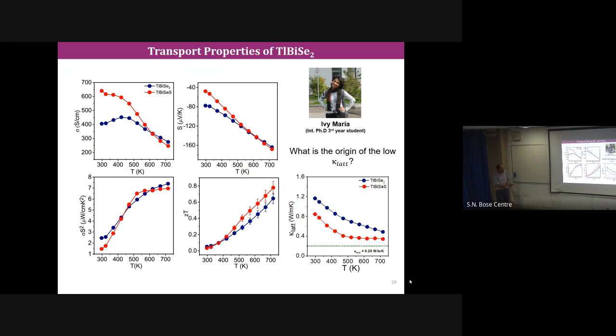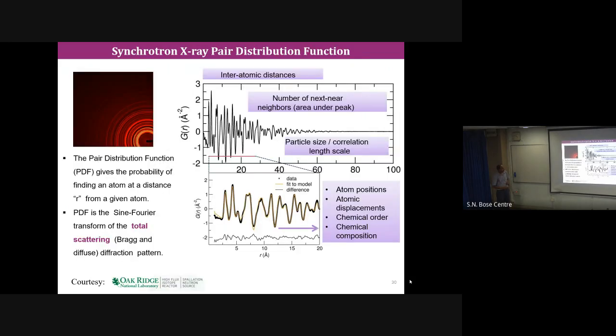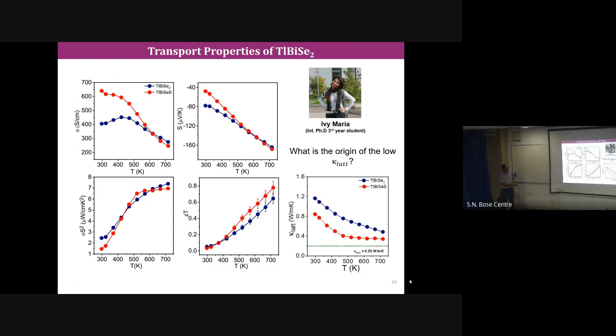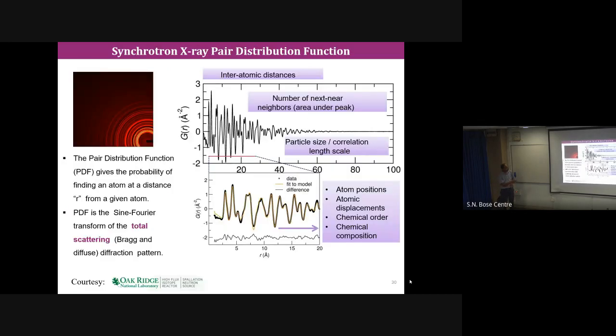So then we try to understand what is happening here. Why does the compound show very low thermal conductivity? Because you see, without nanostructure it touches almost the glass level, right? So what is happening? Then we have done synchrotron X-ray pair distribution function analysis. This experiment has been done at PETRA DESY.